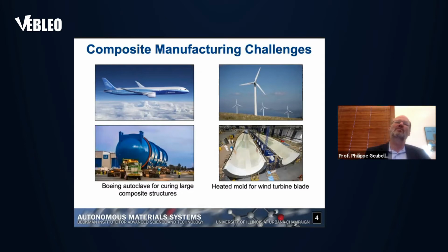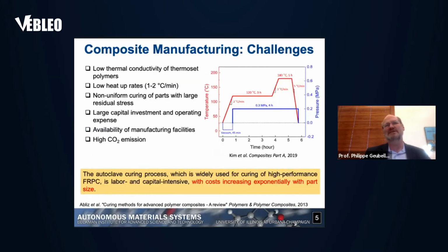What we would like to do is to really speed up the process and reduce the cost and complexity of it. The challenges are due to the fact that in these autoclaves, these materials are subjected to fairly complex temperature and pressure profiles. The temperature profile here is a function of time in hours. The red curve corresponds to the temperature profile, the blue one corresponds to the pressure.